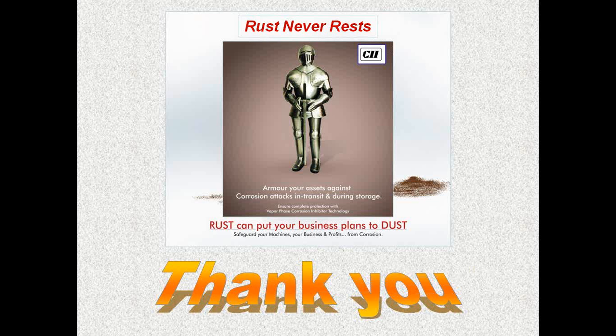Okay, the life of the cooler, you say 1 year. And stainless steel you want, because you have to tell me also what the total process is from starting chemical to final. You are doing a calcination process at high temperature. The simple solution I will tell, if you are trying to use, it must be 310 stainless steel. But you want to go from 950 to 250. 950 is the upper limit of austenitic stainless steels. Offhand I can tell 310 stainless steel, but I will need much additional information to answer you. And CII has promised that they will put the presentation up later also.